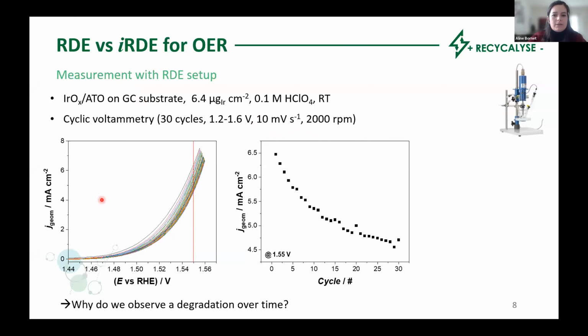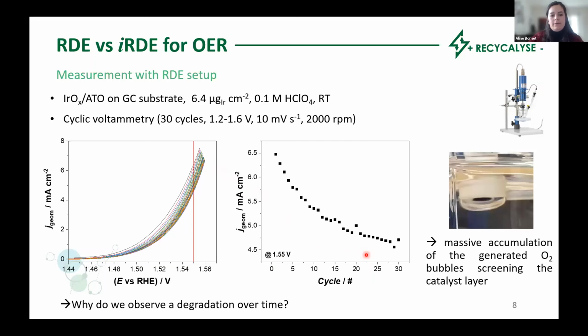On the left-hand side graph, the forward scans of the CVs are plotted, and on the right-hand side plot, we can see the evolution of the current density over the different cycles at a fixed potential of 1.55 volt. And we can clearly see a decrease in the current density over time. And the question is why?